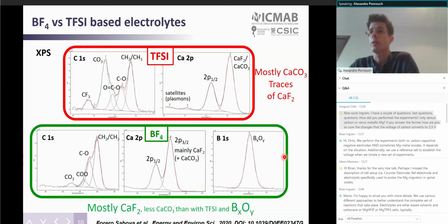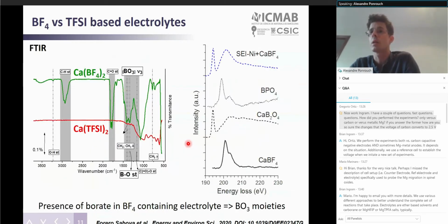From XPS measurements, we observe that both passivation layers contain calcium fluoride and calcium carbonate. But in the case of the BF4 based electrolyte, the passivation layer was significantly richer in organic compounds and also contains borates. We do not yet know the complete chemistry of these borate compounds, but from infrared spectroscopy as well as electron loss spectroscopy, we could identify that these borates are in fact BO3 moieties, trigonal.